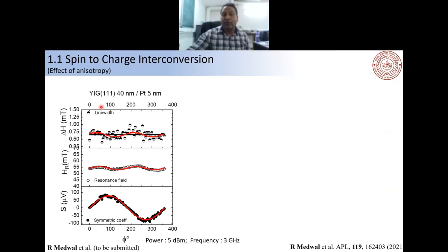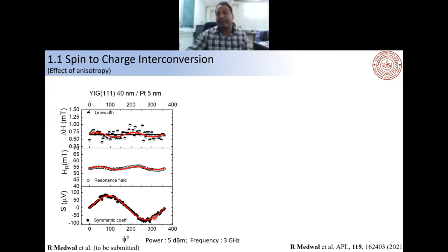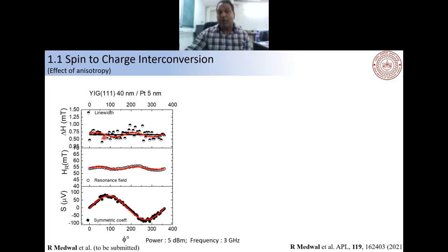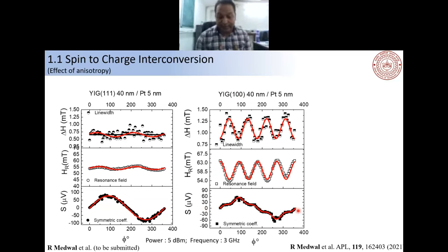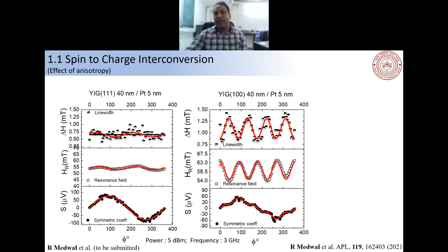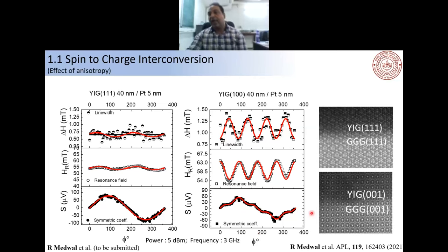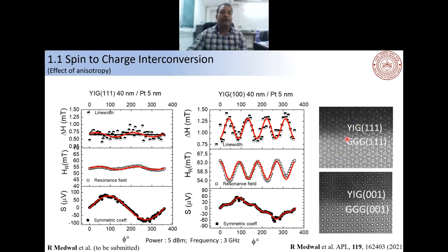The interesting result is how we can control spin pumping from YIG. For YIG(111), 40 nm film with out-of-plane excitation, the symmetric component of the ISHE voltage follows a clean sine θ dependence. But for YIG(100), there is a modulation on the sine θ. We find this is due to the fourfold cubic anisotropy — both the resonance linewidth and the symmetric ISHE component change as a function of in-plane magnetic field orientation, consistent with our TEM results.